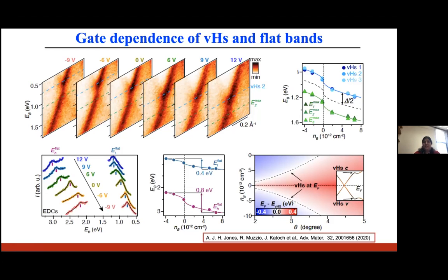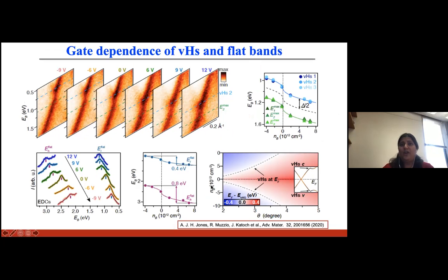Furthermore, from our data, we can extract and plot the phase diagram, which describes the Van Hove singularity binding energy with respect to the Fermi energy as a function of the twist angle and the doping of the bottom graphene layer. And so our results here establish a route towards accessing this emerging phenomena associated with Van Hove singularity physics for a wide range of superlattice heterostructures.